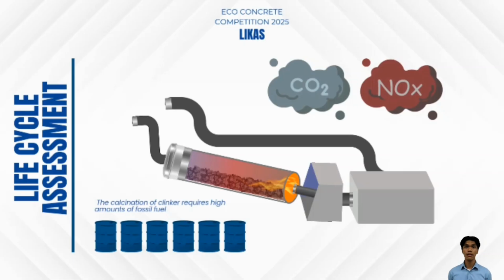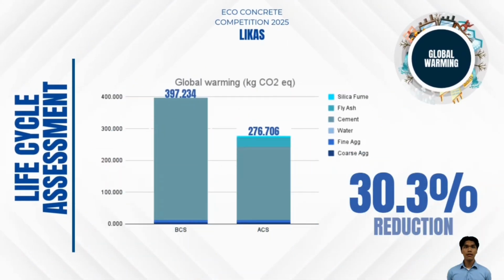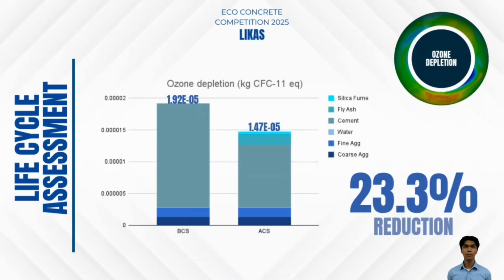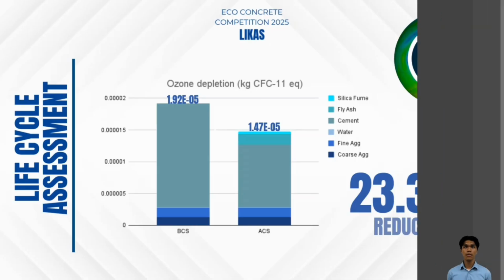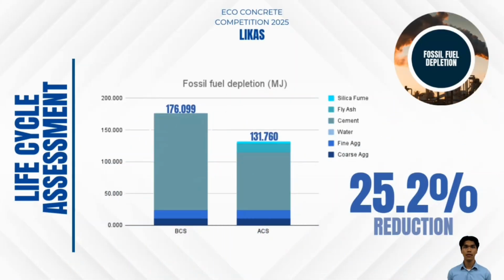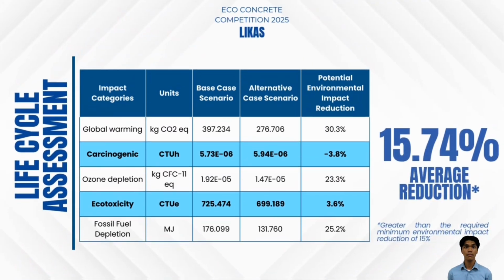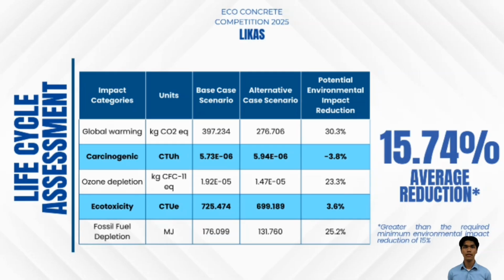The toxic components of cement also contribute significantly to ecotoxicity. Reducing portland cement usage through replacements of fly ash and silica fume leads to a 30.3% reduction in global warming emission, a 23.3% reduction in ozone depletion, and a 25.2% decrease in fossil fuel depletion. These reductions highlight the emission and energy efficiency benefits of SCMs. Improvements in ecotoxicity and carcinogenic impacts are comparatively smaller.